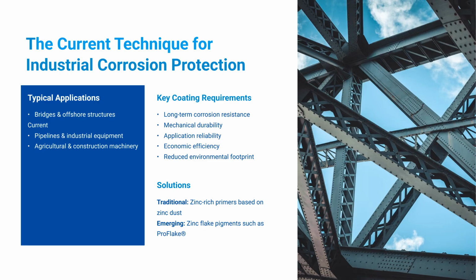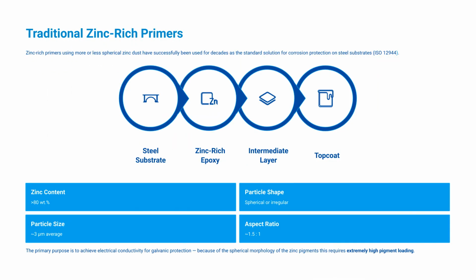One of the most promising alternative solutions is zinc flake technology, which can provide equivalent or improved corrosion protection while significantly reducing zinc content. The traditional zinc-rich primers are defined by ISO 12944 and SSPC Paint 20 to guarantee proper application and film build. According to these standards, zinc-rich primers contain more than 80% zinc by weight. The zinc particles are generally spherical or irregular in shape, with an average particle size of around 3 microns.